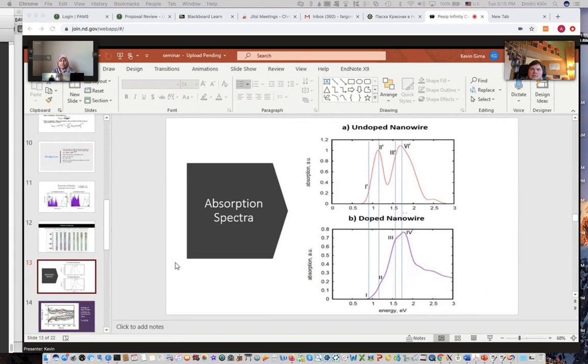And then here we have my absorption spectra for the undoped nanowire, panel A, and the doped nanowire, panel B. If you look at both, both 1 prime and 1 are dark transitions. The number 1 here corresponds to the transition between A prime and A on my earlier density of states, and that's congruent with our expectations. We expect it to be dark because all the orbitals are localized near those states A prime and A.